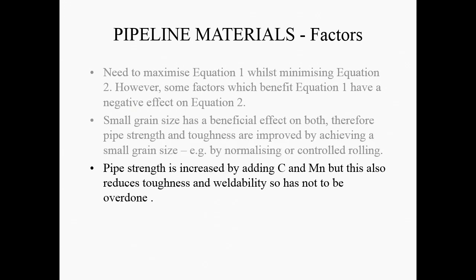So the pipe strength is increased by adding carbon and manganese. And some of the higher grades, they do that. All mild steel, every piece of steel that you get has carbon and manganese in it. Manganese is added in as a deoxidant in the steel making, and carbon is there obviously to give you the strength that you want. But you don't want to put too much, because both carbon and manganese will reduce toughness and weldability. So you have to have some carbon and manganese there, but you don't want to put too much.